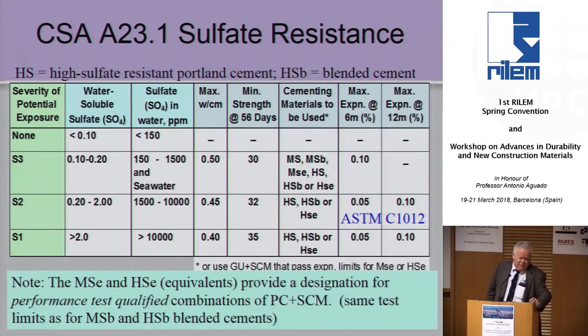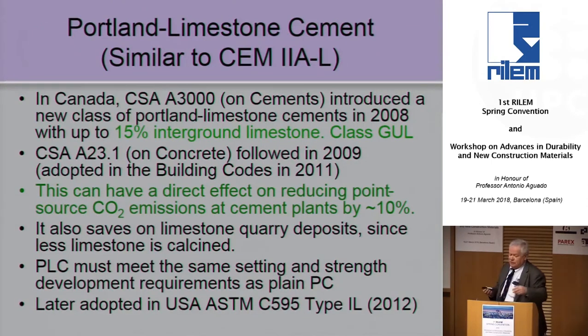As a result, our specifications for sulfate attack are very similar in Canada and the US. It's a simplified program, less complex than the EN standards for sulfates. We just simply have 3 categories of different severities, and we decrease the water-cement ratio as it gets more severe. We have requirements for cement, moderate sulfate-resistant or high sulfate-resistant cements, and we can qualify mixtures of blended cements or mixtures of SCMs, supplementary cementitious materials, and Portland cement by using a mortar bar expansion test. So we have this option, and that's been working for us and pretty much has solved problems, except when we introduced limestone about 10 years